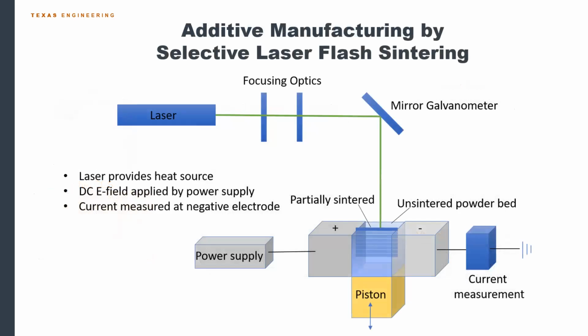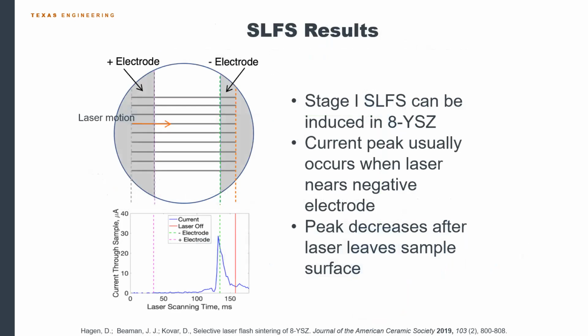So the second method that I've mentioned to get over the limitations with ceramics is this process we call selective laser flash sintering. And mechanically, this process is very similar to the SLS process. All the mechanical components are the same, except for the fact that we add an electric field across the powder bed. You can see that there's a power supply attached to a positive electrode, and then we measure the current at the negative electrode.